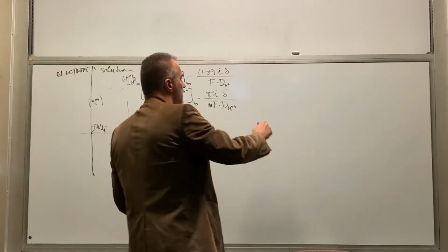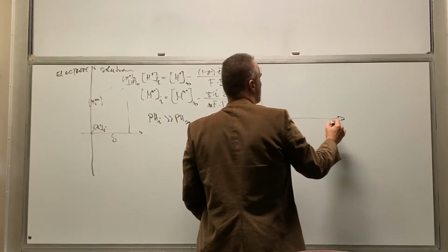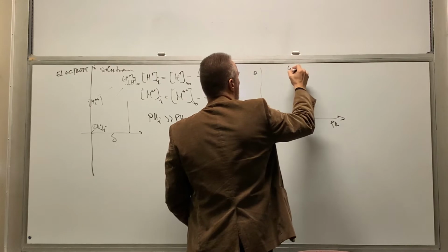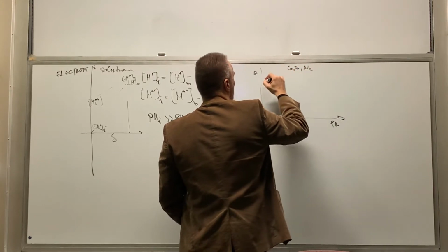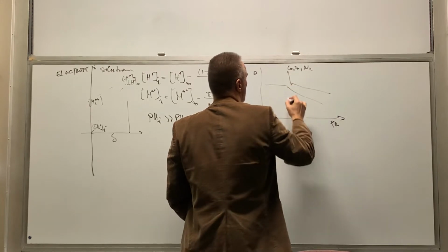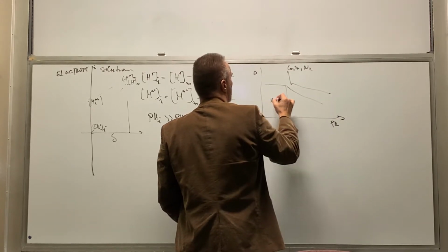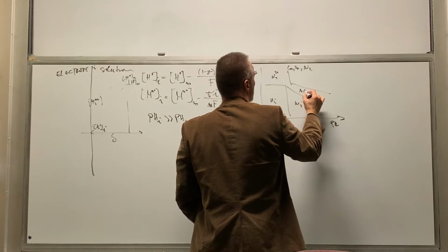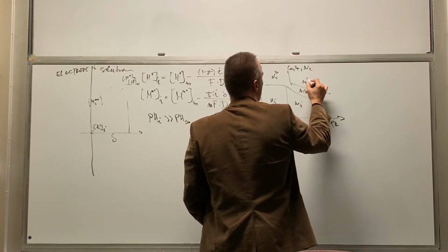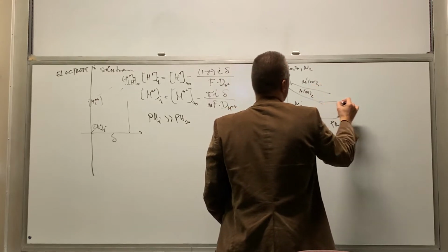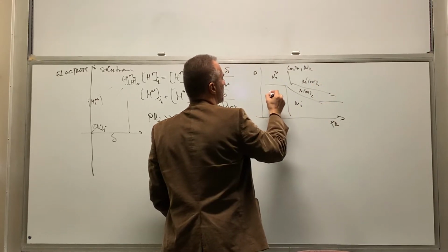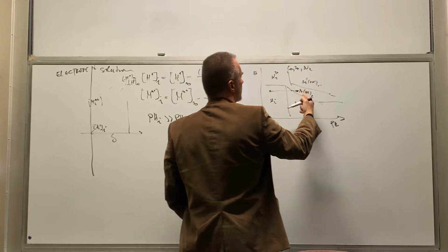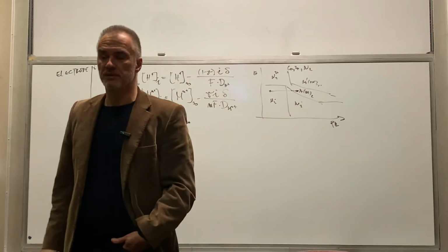And then we said if we are looking at the Pourbaix diagram for a typical metal, whether it's cobalt, iron, or nickel, it's going to look something like this, where this is nickel 2 plus, and then this is nickel, but then here's the nickel hydroxide, nickel higher oxidation states, etc. And that's the problem, because if we are applying potential and depositing nickel at the interface, we might actually also get some nickel hydroxide precipitating.